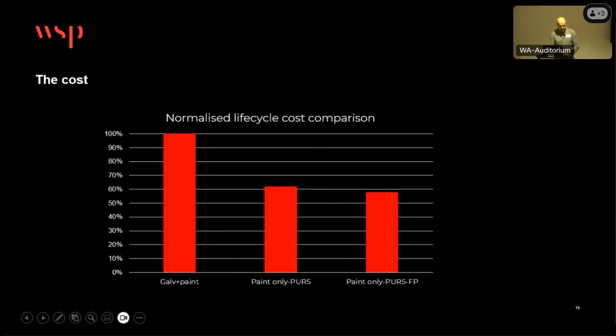We found that the service life between maintenance intervals would be at least twice that of a comparable polyurethane-based coating system. The cost data indicated that there would be an initial capital cost premium of around 10% to apply that coating compared to a PURS system. However, once we compared the number of coats that you would need to do over a 120-year life, we estimated you might need 3 for a PURS, where you could possibly get away with potentially one recoat for a PURS-FP or fluoropolymer-based system.